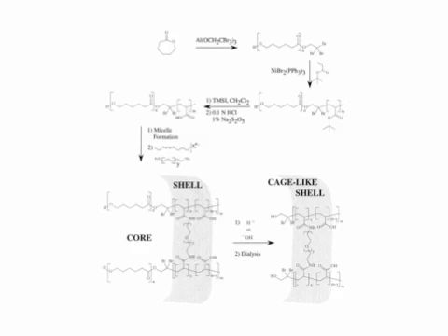An acid you can react in this particular case with an amine in order to turn it into an amide, and therefore you need to do a coupling reaction. So you have this coupling agent that's water soluble that makes that reaction work really well, and then you've got a cross-linked shell. And then this polyester, which was the hydrophobic part, can be degraded out. So then you'll have your cage-like hollow nanostructure. Yeah? And you just have to be creative with your organic chemistry and polymer chemistry to make these kind of things.